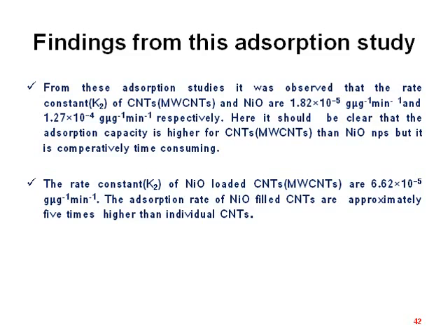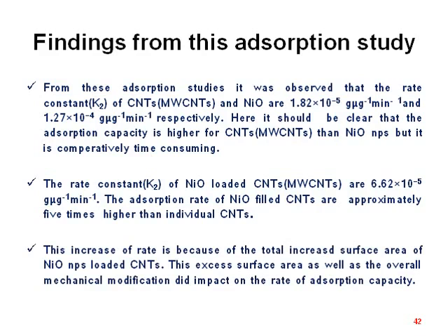The adsorption rate of nickel oxide filled CNTs is approximately 5 times higher than that of the individual CNTs. This increase of rate is because of the total increased surface area of the nickel oxide nanoparticle loaded CNTs. This excess surface area as well as the overall mechanical modification did impact the rate of adsorption.